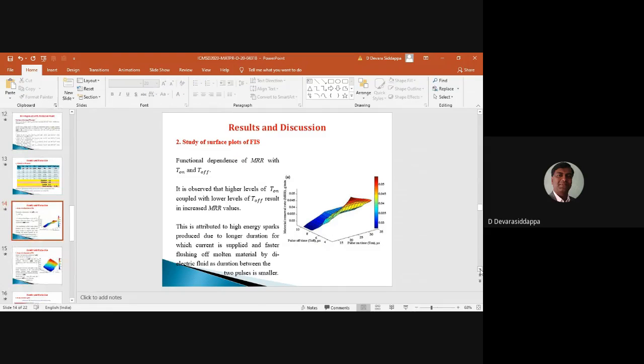The second part of the results and discussion is the study of the surface plots of the FIS. The fuzzy logic modeling gives the option of drawing the surface plots for the entire rule base. So we have taken the 2 important parameters, pulse on time and pulse off time. As you can see, higher values of pulse on time and lower values of pulse off time result in higher MRR values. This can be attributed to high energy sparks produced due to longer duration. For more duration, the current is drawn during higher values of pulse on time, and at lower values, faster flushing of molten material is possible, which results in higher MRR.